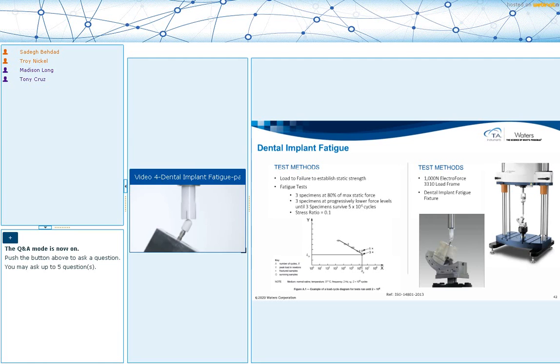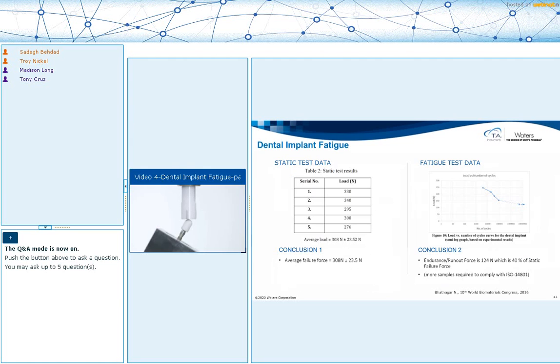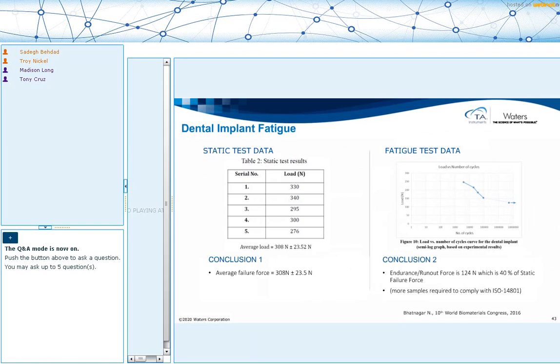So going to the results of this study, this is a study, by the way, done at IIT in India, and they didn't have many samples in their hands because this wasn't done in academia, so they tested one sample for each point of their S-N curve. So if you want to comply with the standard, you got to test more. But the concept remains the same. So they tested 5 samples to failure, and the table on the left is showing you those 5 data points. They averaged those, and they measured that the average load to failure is going to be 308 newtons.